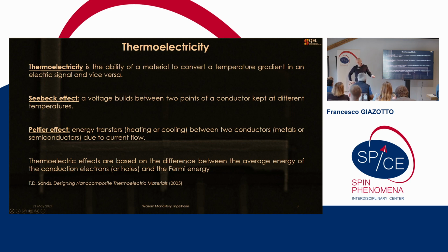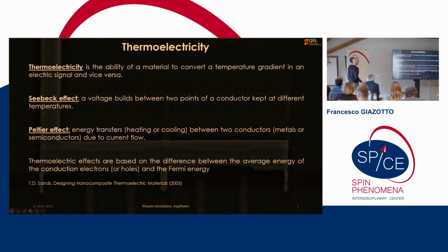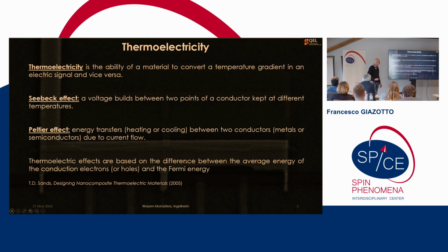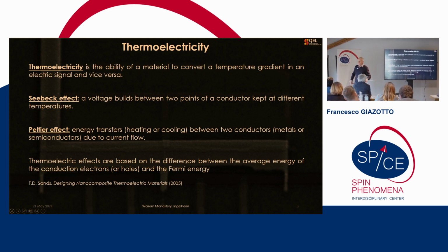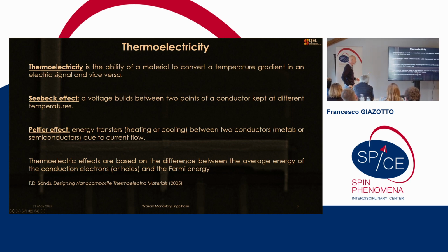And in general, what is known is that thermoelectric effects are based on the difference between the average energy of the conduction electrons or holes and the Fermi energy. So in the general knowledge of scientists, you can achieve a proper thermoelectric response if your system is sufficiently electron-hole asymmetric.